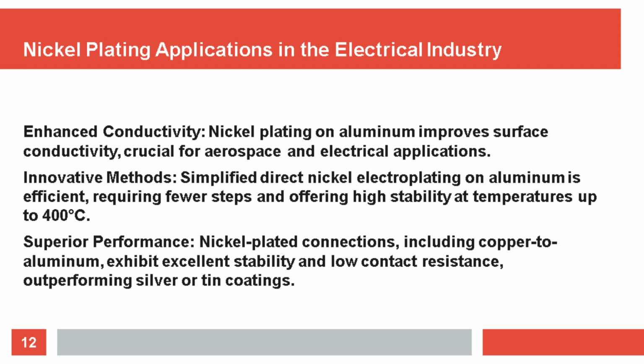Nickel plating has been put through the paces, even on copper bus bars bolted to aluminum. And guess what? It showed excellent stability and started off with low contact resistance. In fact, tests have shown that nickel-plated copper to aluminum connections perform better than those plated with silver or tin, no matter the conditions they're put through.